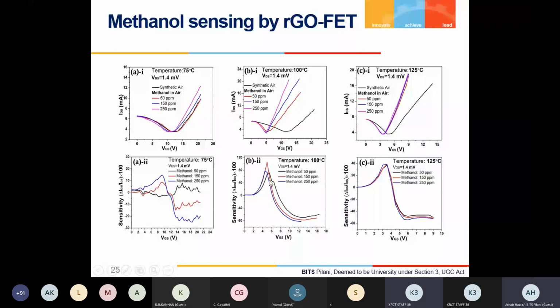This is shown at different temperatures. At 75 degrees centigrade, here is the maximum sensitivity. At 125 degrees centigrade, here is the maximum sensitivity. So at a particular gate voltage we are getting the maximum sensitivity, and we should fix that particular gate voltage to get the highest sensitivity in case of sensing. That thing we did now.